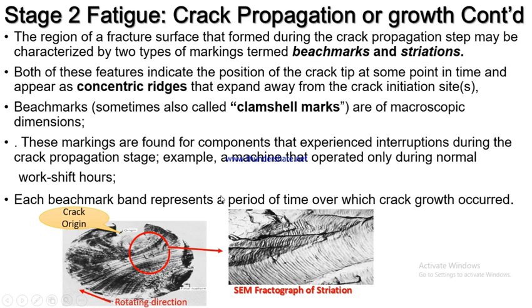This is a particular crankshaft. Here you can see the crankshaft. I will assume that the rotation of the crankshaft is in this direction, and the crack originated from this place. When the crack originated from this place, the crack began to propagate towards this place, and finally the final fracture took place at this particular zone. In the other part of that slide, I will explain how, from final fracture and rapid fracture, we can know the places where cracks initiated in materials.